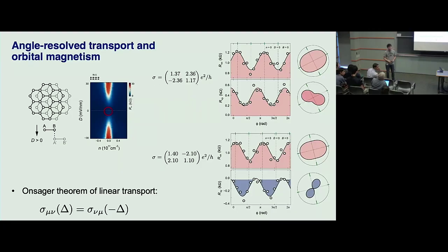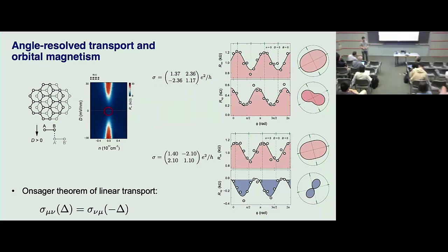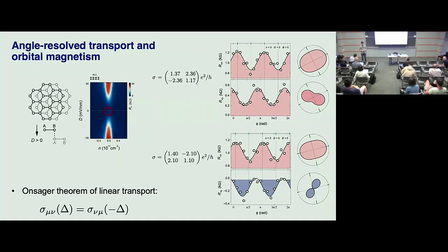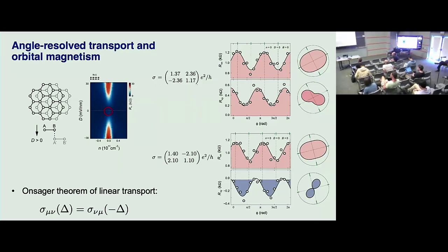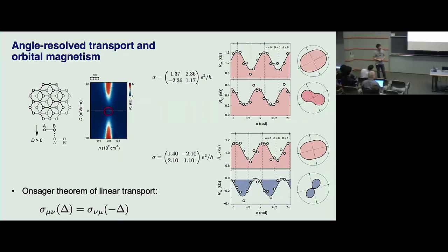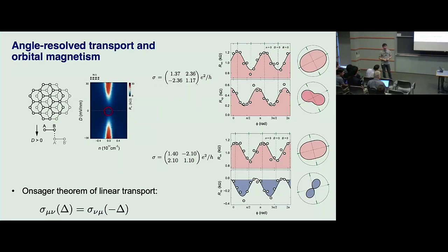So for the conventional Hall configurations, all these papers with the nonlinear Hall effect, I just want to clarify: are you saying you cannot conclude anything regarding a nonlinear Hall effect without doing this angular dependence? Yes, you cannot conclude anything from just doing the Hall measurement. The nature of a nonlinear tensor is that every component has its own angular dependence. If you just look at one direction, there's no way you can tell between these many different configurations of the tensor.